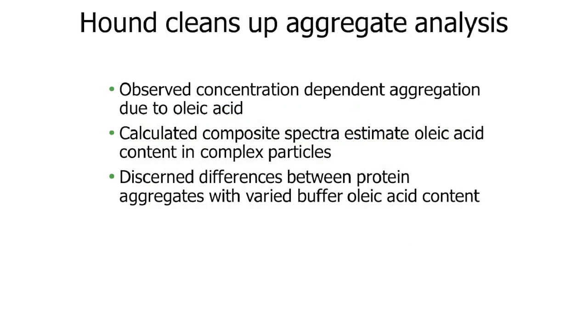While it was initially suspected that oleic acid was inducing protein aggregation, Hound confirmed that there is in fact a concentration-dependent aggregation due to oleic acid in the buffer. Using the calculated composite spectra that we talked about, Hound was able to discern differences between protein aggregates with various concentrations of buffer oleic acid and even estimate the relative percentage of oleic acid content in these complex mixed particles.